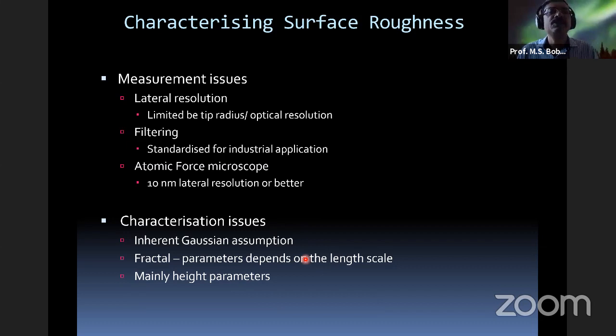There are some measurement issues. There are some lateral resolution limits. As we said, we always have to use a sharp tool to measure, in a contact profilometer or in an optical microscope or optical profilometer. Optical resolution is decided by the wavelength of the light, which is about 600 nanometers, and that will be the limit of the lateral resolution. Atomic force microscope can give you a lateral resolution of 10 nanometers or better. And there is also a vertical resolution. Vertical resolution can be very, very high, but the problem is lateral resolution.